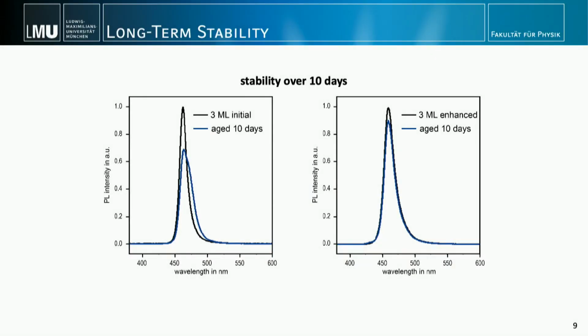So we talked about tunability and efficiency. We're coming almost to the end. We quickly talk about stability. Here we showed that by the repair process, the long-term stability over 10 days could also be improved. You see the first panel on the left, where we don't do the treatment.